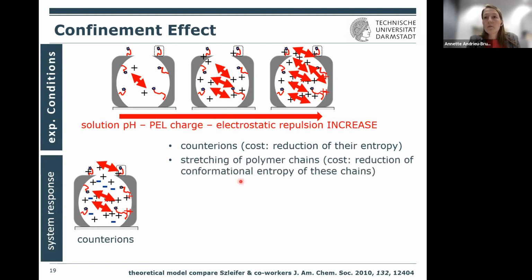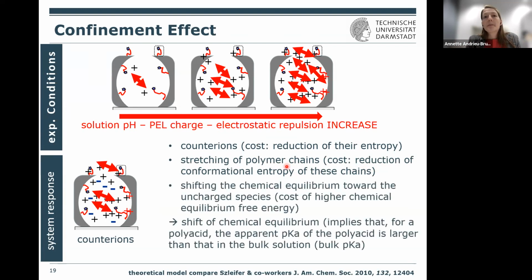You can stretch the polymer chains to increase the distance. This is again at the cost of reduction of the conformational entropy. And you can shift the chemical equilibrium. This means, if you talk about pH, for example, let's say usually this polymer has a pKa value of 4. Now you have to bring in more energy to get the same charge situation that you would achieve at pKa 4. So this pKa value would be shifted.